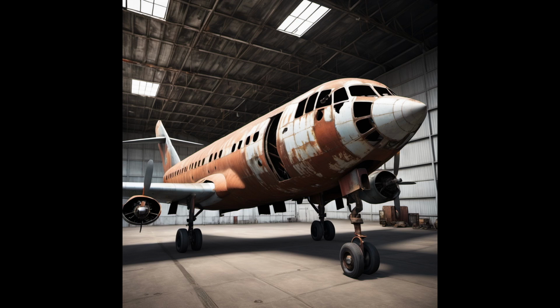During the first stage, the combined action of corrosion and cyclic stress damages the metal by pitting and crack formations to such a degree that fracture by cyclic stress occurs, even if the corrosive environment is completely removed. The second stage is essentially a fatigue stage, where failure proceeds by propagation of the crack, often from a corrosion pit or pits. It is controlled primarily by stress concentration effects and the physical properties of the metal. Fracture of a metal part due to fatigue corrosion generally occurs at a stress level far below the fatigue limit of an uncorroded part, even though the amount of corrosion is relatively small.